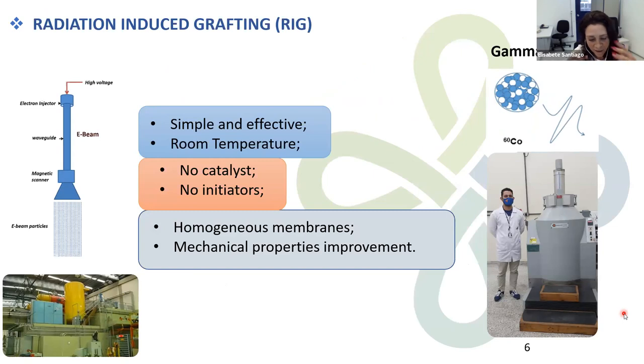The copolymerization, I mean the attachment of side chains into the backbone, is also called grafting, and it can be done by using high energy radiation, for example electron beam or gamma ray. The method of this attachment is called radiation-induced grafting, or RIG. The advantages of using radiation are that the method is simple and effective. You can do it at room temperature, and I don't need catalysts or initiators to promote the grafting reactions. It can lead to homogeneous membranes with good mechanical property improvements.